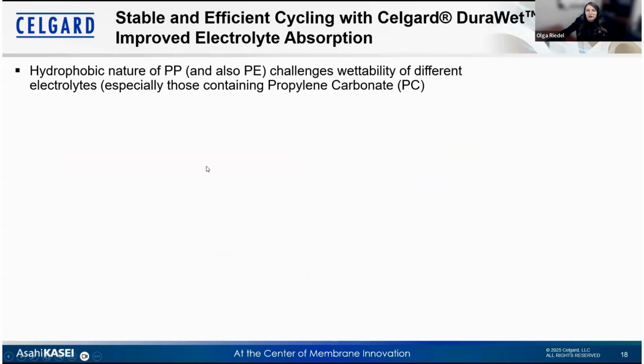Let's talk about electrolyte wettability for a minute. The hydrophobic nature of polyolefins, this is true for polypropylene and polyethylene, can be challenging for wettability at times. This is even more true since cell designers continue to push the boundaries to larger and larger formats, like the 4680 cells, but also the 600 ampere-hour plus prismatic cells. Electrolyte retention and absorption becomes really critical in this type of large cells.